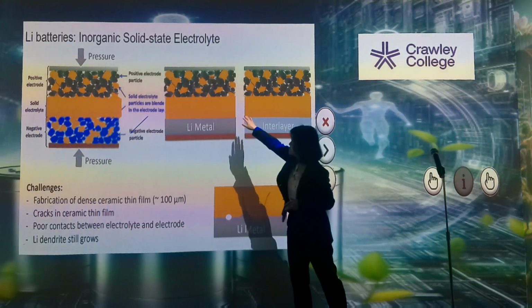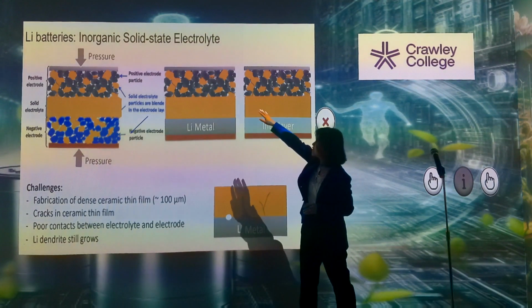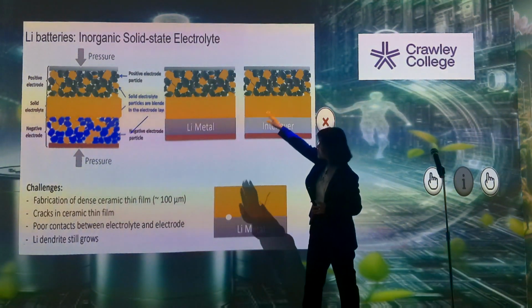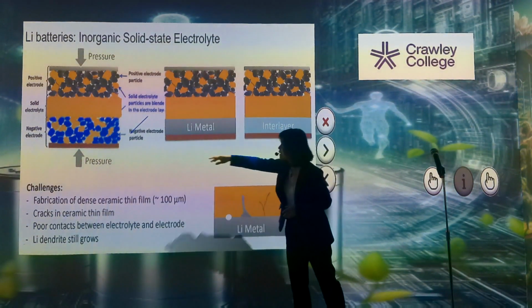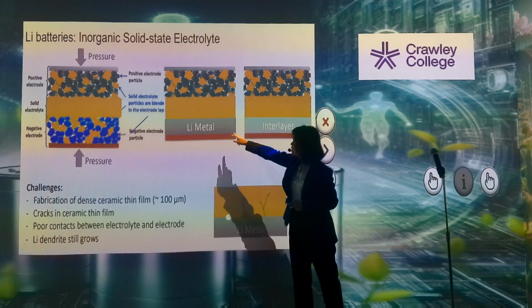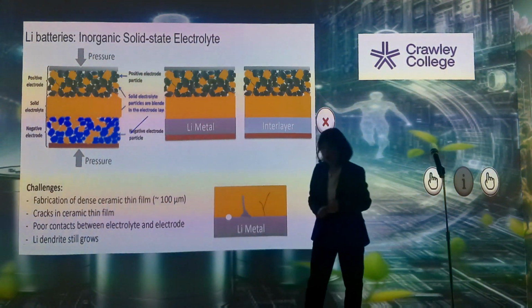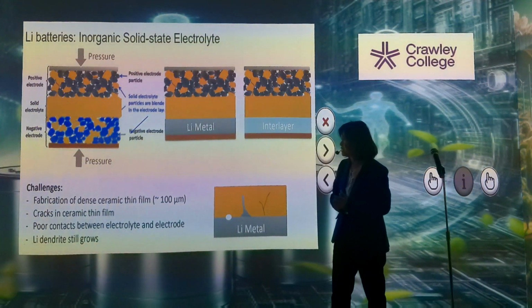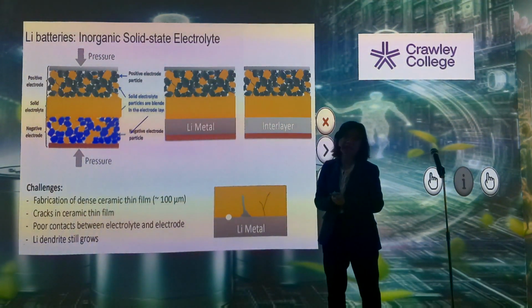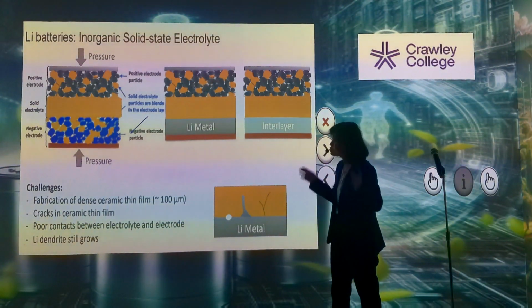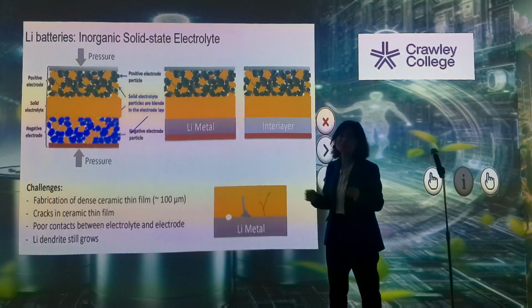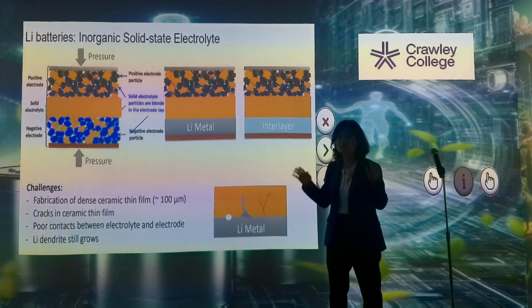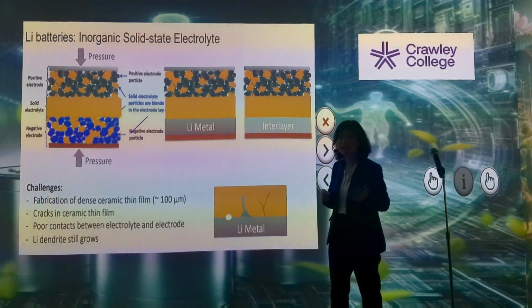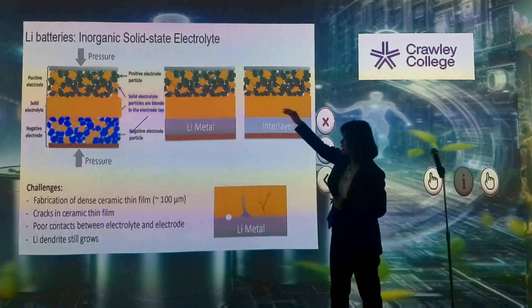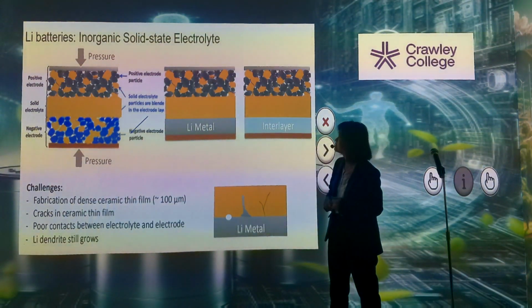So in the middle is the solid-state electrolyte, and then you have the cathode, which is the active material mixed with solid-state electrolyte particles, and then you can have the normal anode, or you can use lithium metal now as the anode. The challenge with this type of battery is it's not very easy to fabricate the dense ceramic thin film, typically around 100 micrometer. It's very thin, and it does require a lot of art and experience to make that kind of ceramic thin film, very robust one, because they are very easy to crack, especially in this kind of solid state batteries.